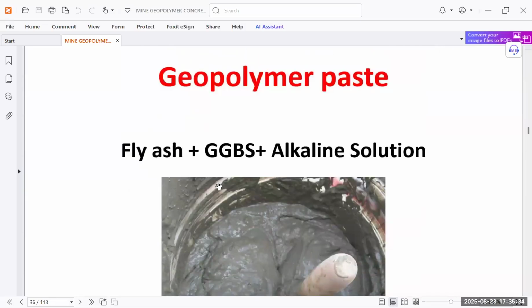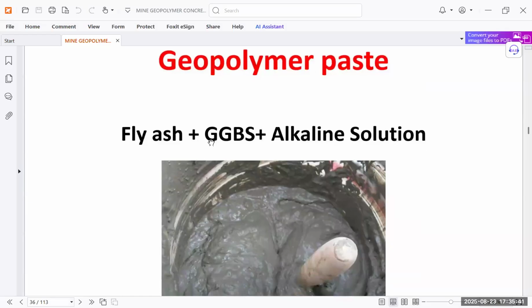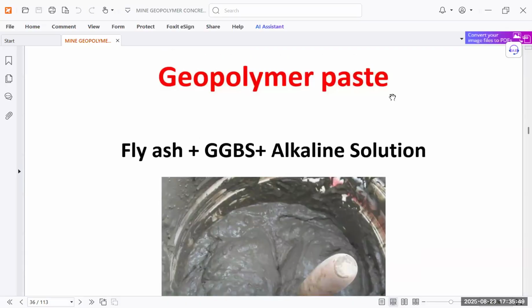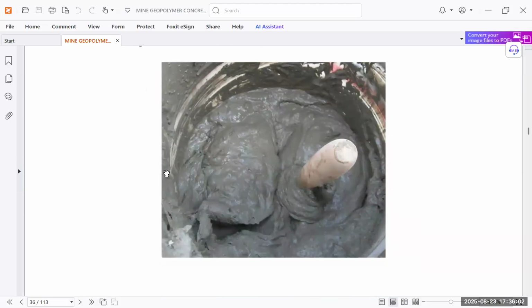And geopolymer paste is made by fly ash plus GGBS with alkaline solution. In this we are using source material as GGBS, ground granulated blast furnace slag, and this alkaline solution with fly ash. So this makes the geopolymer paste. You can see the cement is not there in this paste. That is missing here. That is the change in this geopolymer concrete we have made, so that our requirement of CO2 is less and carbon footprints are less.